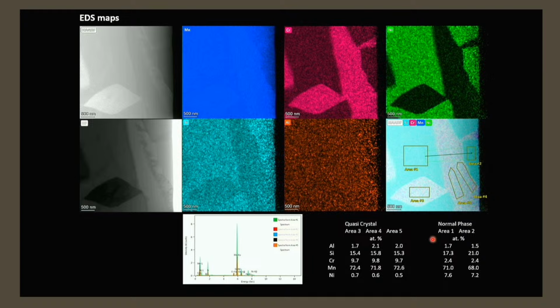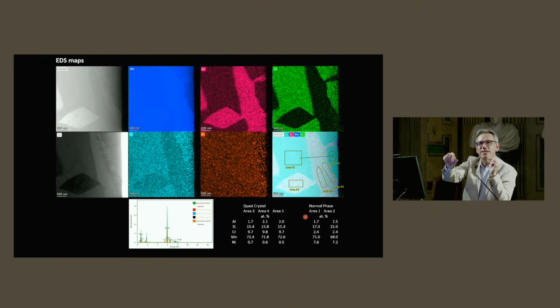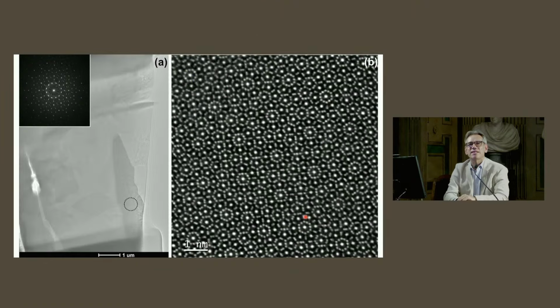What is very interesting is that when you try to cut it out and obtain an electron diffraction pattern from the acicular grains, you get a perfect dodecagonal symmetry. So it is a quasicrystal, a dodecagonal quasicrystal with 12-fold symmetry.